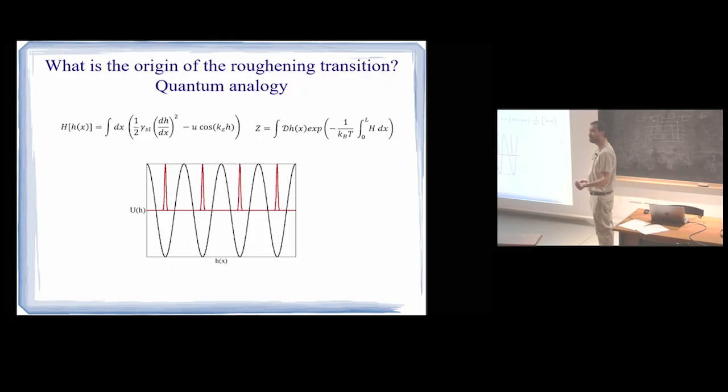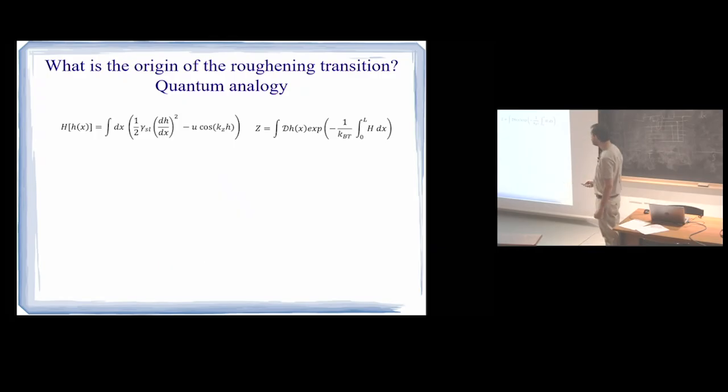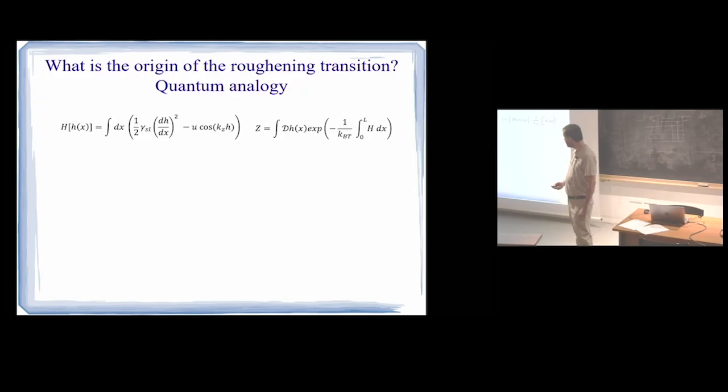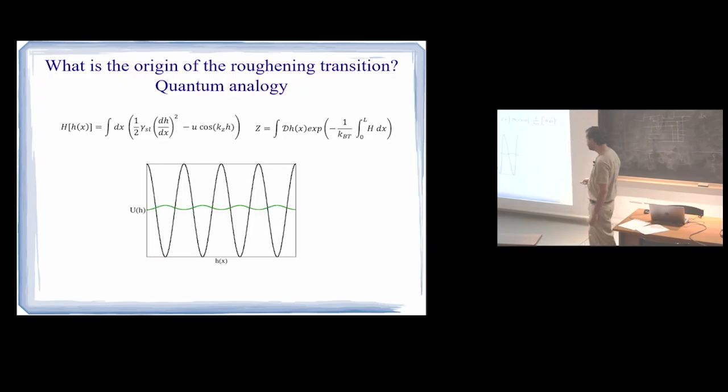Okay? Now, if you increase the temperature, the surface tension decreases. This is like becoming less heavy, and you get closer to a quantum situation, and then your distribution is going to broaden. Still, the distributions are localized, but they are broadened. But if you decrease the mass further on, then the distributions start to tunnel. They are tunneling. And eventually, at sufficiently low surface tension, that is sufficiently small mass, you become an electron. And you behave fully as in quantum mechanics.